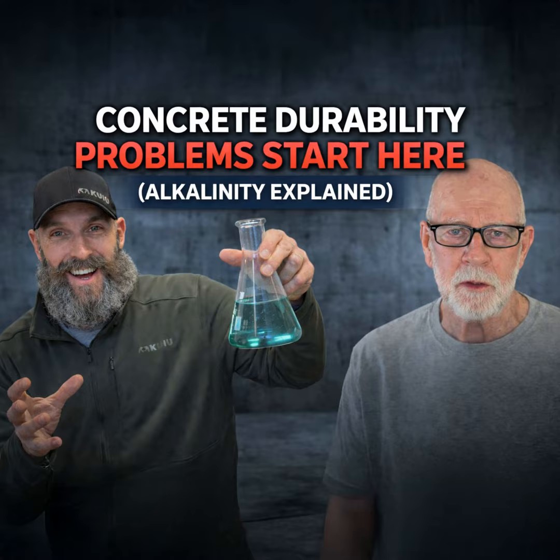It's an excuse. So where are all the salts coming from? That occurs naturally in the aggregate, in the concrete, and it's also coming from the cement now with the cement kiln dust. Because cement kiln dust, and unfortunately I didn't screenshot it, but there was one recorded example where the alkalinity was 400% higher with the cement kiln dust than it was in the cement without the kiln dust. So it's pretty dramatic. So with that concentration of alkalinity coupled with the initial hydration of the cement, now it makes sense why the concrete is self-desiccating towards the surface.